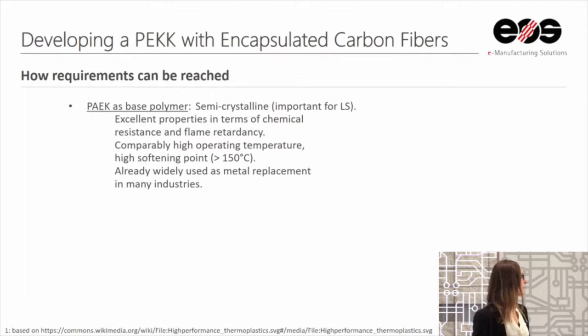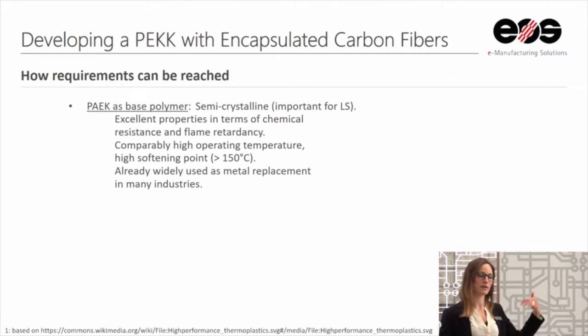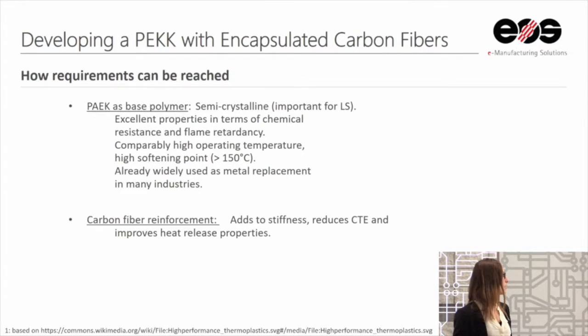And our approach was, again, we looked at those PEKK materials for one reason, because they're on the right side of this pyramid, and all the other additional advantages I was pointing out. And we also decided to do a carbon fiber reinforcement to the material. It has multiple advantages. It adds to the stiffness, obviously, but it also reduces the coefficient of thermal expansion that has a positive impact on the shrinkage. And I will also get to the other, like the isotropic properties are very much linked to the carbon fiber reinforcement as well. I'm going to go into details.